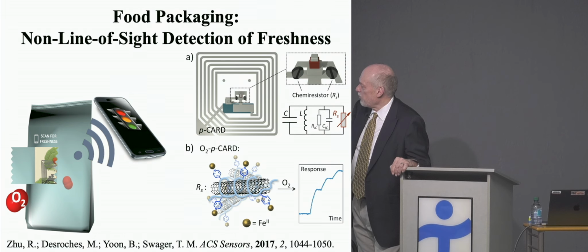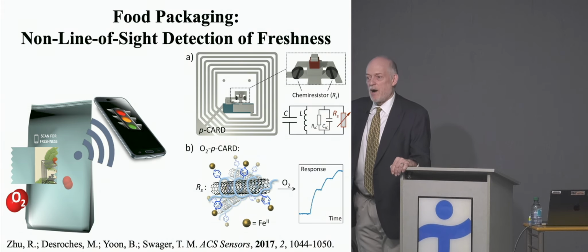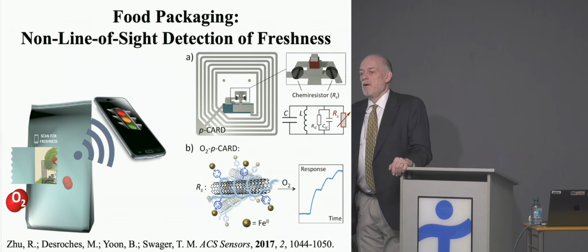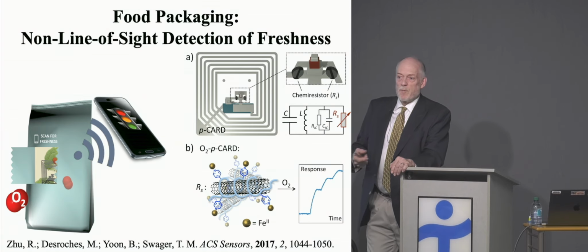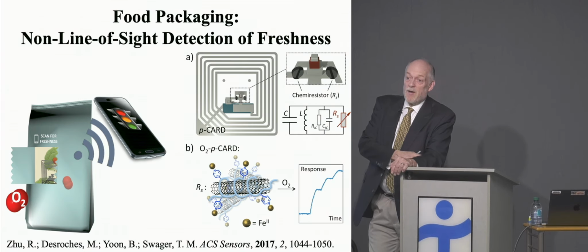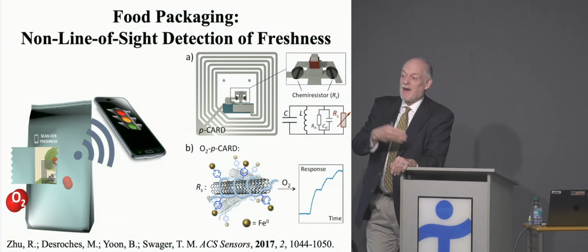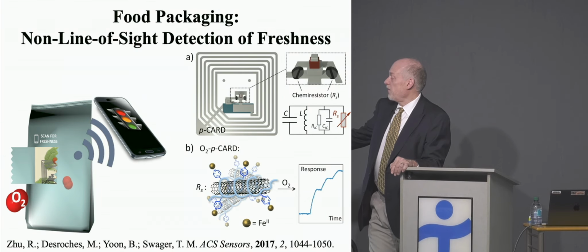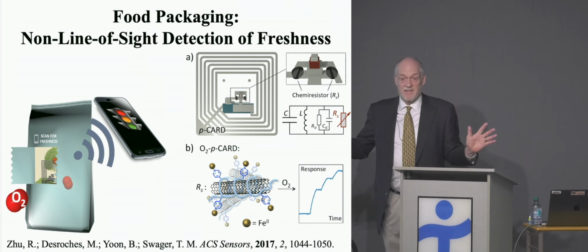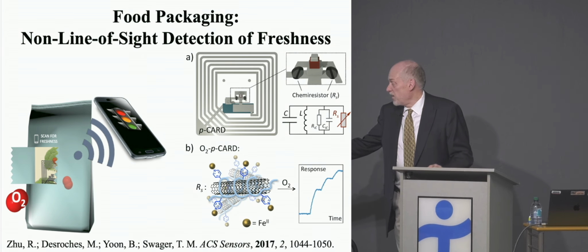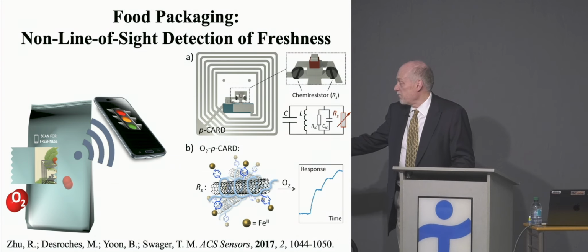And here we took the nanotubes and wrapped them with a polymer, poly(4-vinylpyridine), and we put iron ions on them. So iron in a reduced state. Iron in our blood, when we bind oxygen, is in a reduced state, and our body has to continually maintain it in that reduced state. It will oxidize in air otherwise. But this is iron in that reduced state, which is fundamentally sensitive to air. And when it gets oxidized by air, it changes.